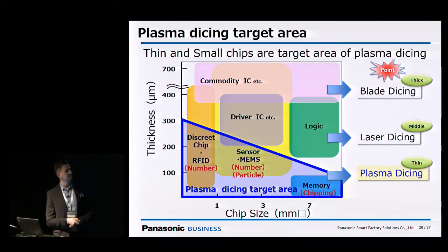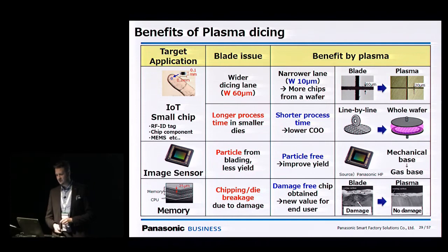As the device gets thinner and the chip size reduces, it starts to get very attractive for plasma dicing, considering those issues that I talked about before: increased yield, and a longer dicing time because of the more devices on the wafer. So in different areas of the industry where advantages can be gained from plasma dicing, you can increase the yield by reducing, for example, from 60 down to 10 micrometers street width. Much faster dicing time, because the dicing is performed on the whole wafer, and it's based on the thickness of the wafer now, not the amount of lines that need to be cut. It's particle-free, which is very important, especially for image sensors. And damage-free, so as I showed you before, the increased strength due to no internal cracking.